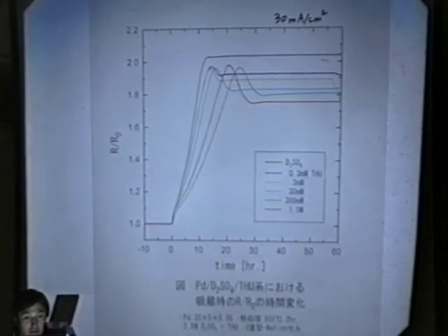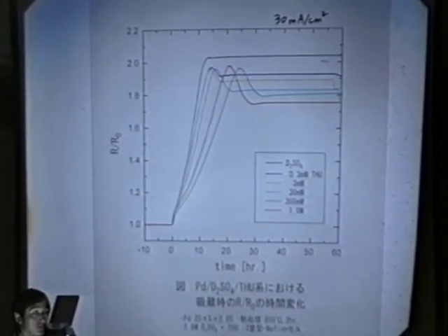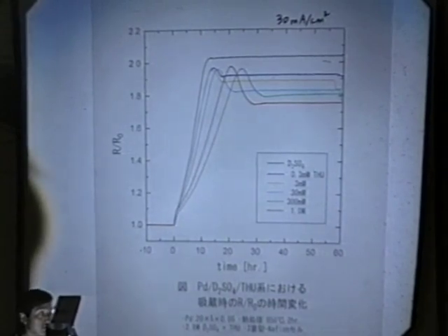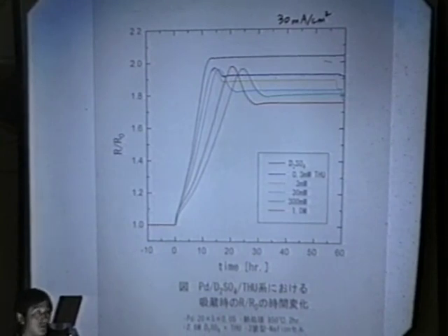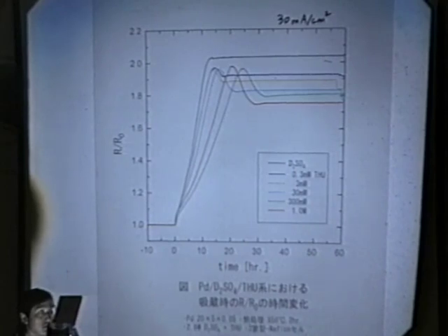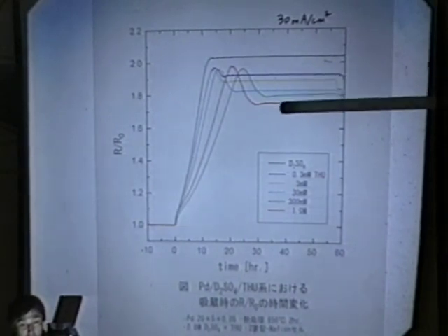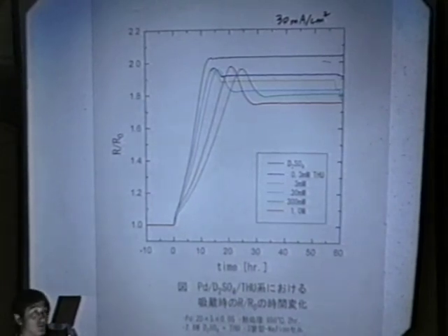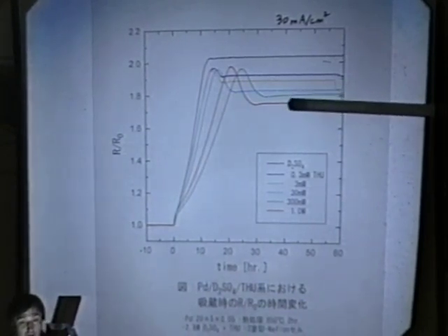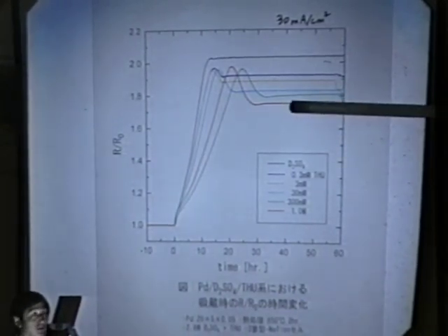So along this line, I'm sure there is a concentration gradient from the surface to the bulk of the palladium sample. In that case, we have found that the apparent resistance becomes lower than the value when hydrogen concentration is uniform. But at this steady state region, we are sure that this sort of concentration gradient has disappeared, and then we can rely on the actual resistance value to see the effect of hydrogen.